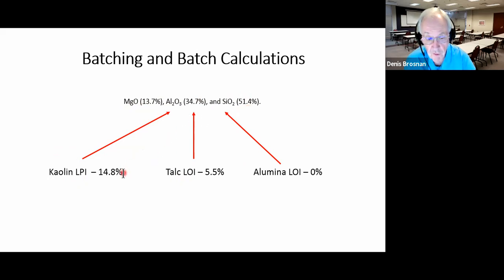Once we have that composition, then we have to go back to an as received weight basis and divide the kaolin by its residual after ignition and the talc by its residual after ignition. And then we'll add all those up and normalize them to 100%. And we've got our batch. In other words, we cannot batch based on the as received weight basis. We've got to convert to calcined basis, meet the composition, and then reconvert to an as received weight basis. You can do this manually. You can do it with Excel. There's a matrix method with Excel that makes this pretty simple.